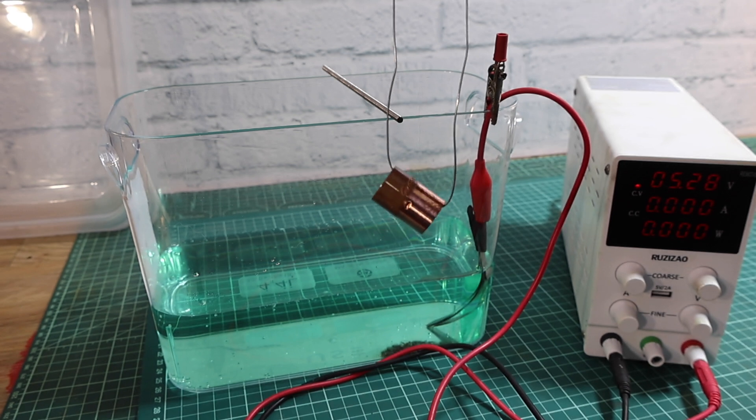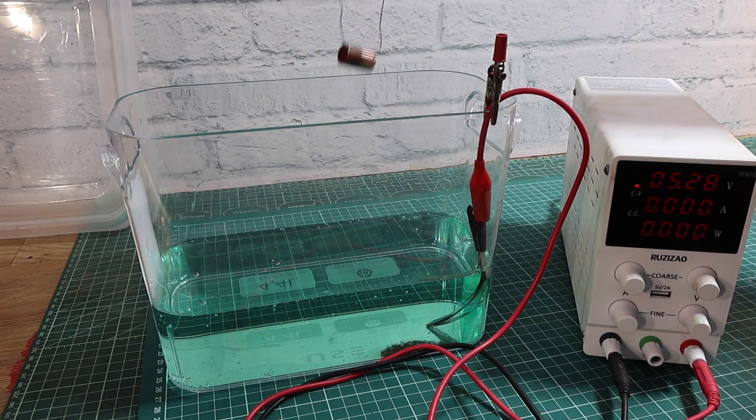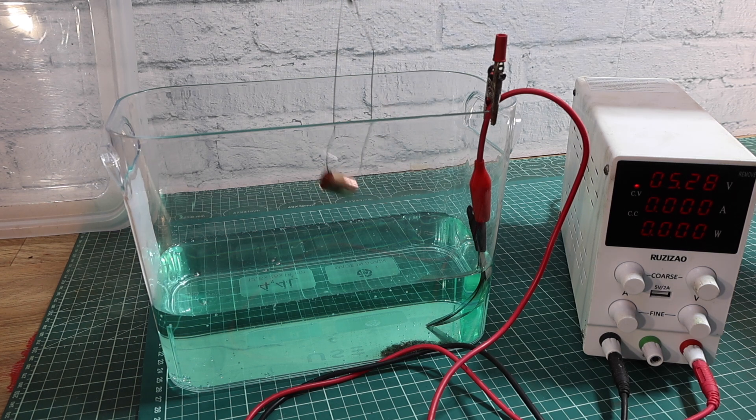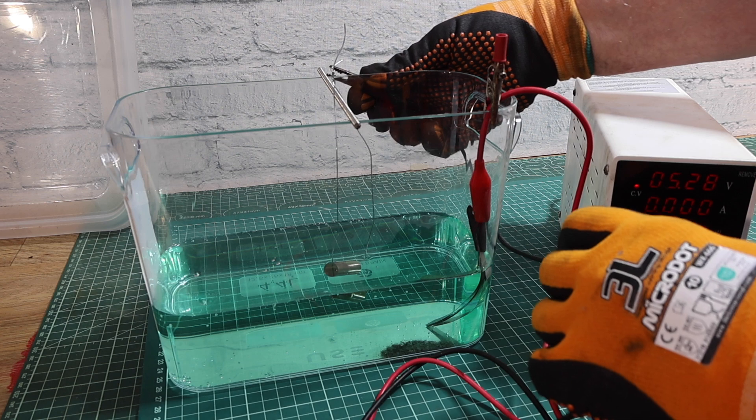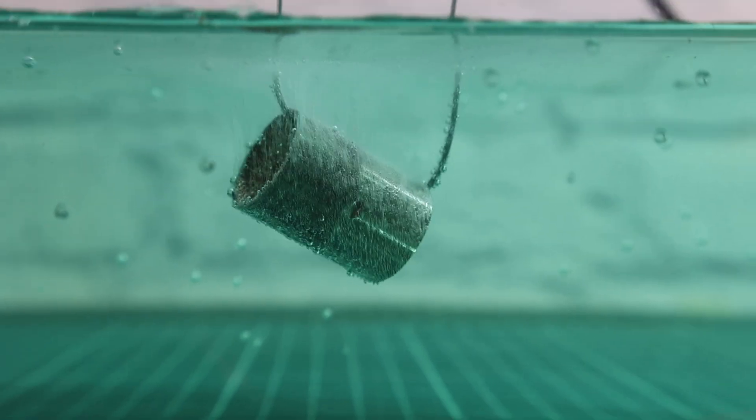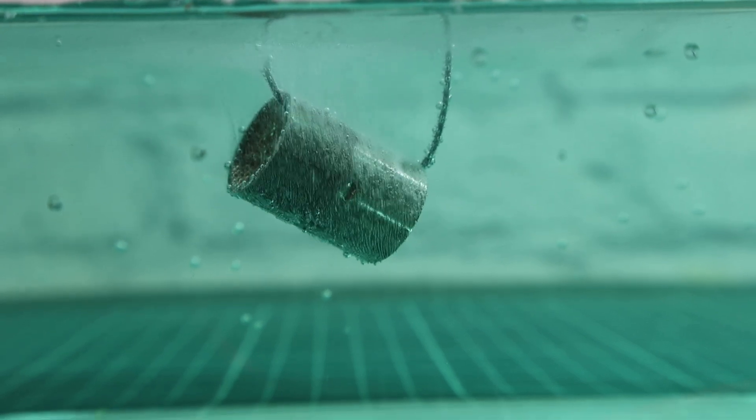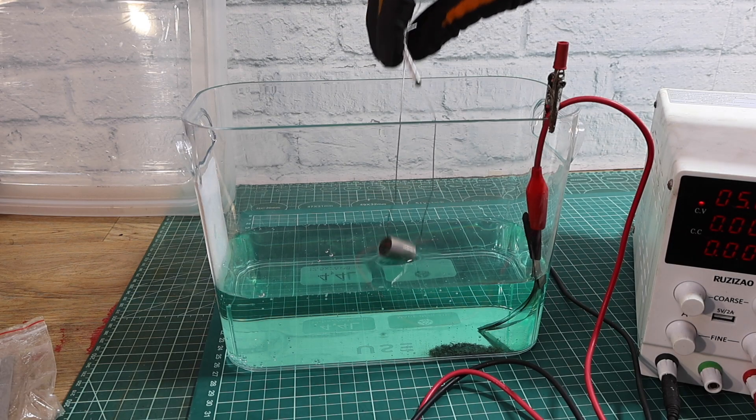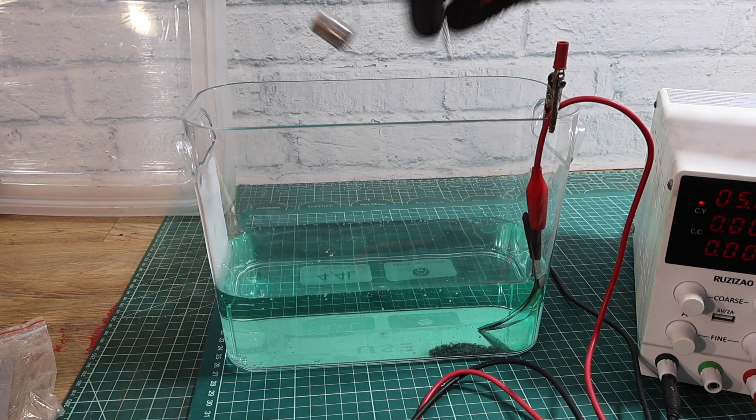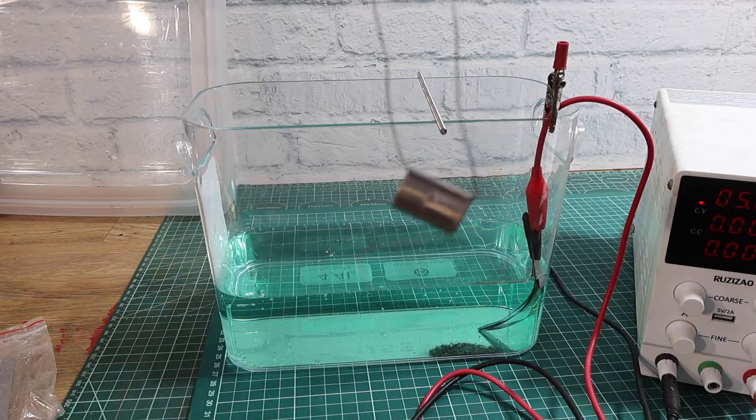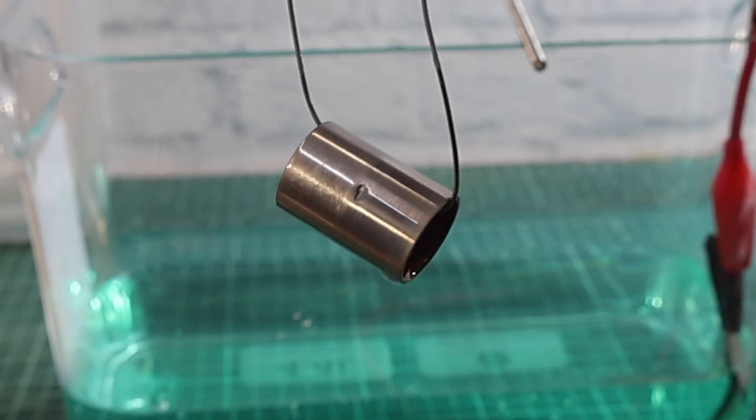Now we've got a copper union. But what I've done here is I've polished up one side of it and the other side is just as it was. See, normally with electroplating, you don't get anything for nothing. It very much depends on the surface finish that you have on the component. So it's well worth getting a good finish on the component before plating. The nickel plating will just basically replicate what's on the component. And you can see the difference between one side and the other.